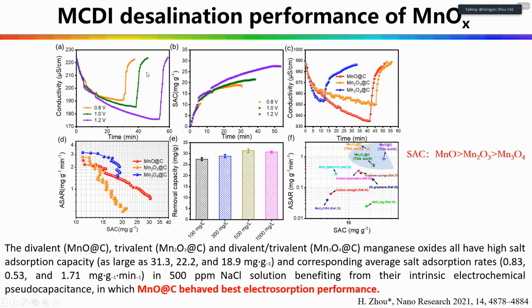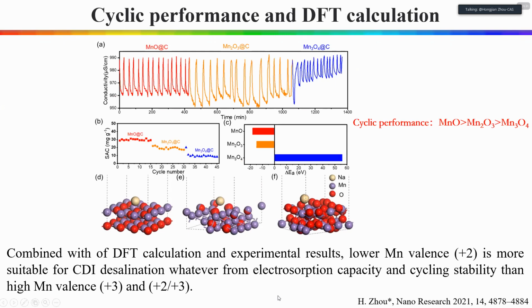And this is the MCDI desalination performance of manganese oxide. We can find that the divalent, trivalent, and mixed divalent-trivalent manganese oxides all have high salt adsorption capacity, and also a good average salt adsorption rate in 500 ppm sodium chloride solution, benefiting from their intrinsic electrochemical properties. The most important part is the lowest-valence manganese oxide. This material shows the best electrosorption performance. Combining DFT calculation and experimental results, we can find that lower manganese valence is more suitable for CDI desalination, both for electrosorption capacity and cyclic stability, than the high manganese valence oxide materials.